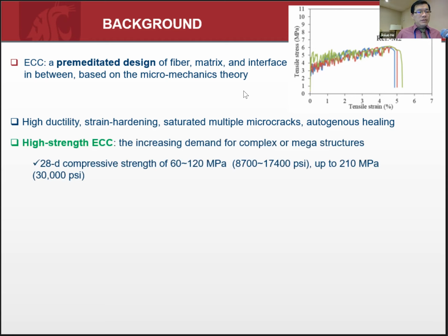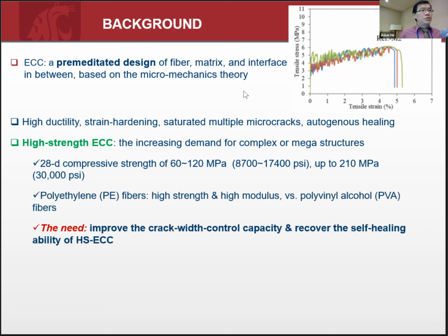Now, in recent years, there's a desire to go for higher strength ECC because traditional ECC is not that high strength. So we're converging with UHPC, even though not reaching the level of UHPC, depending on how you do it. There's some research trying to combine the benefits of UHPC and ECC, but that's not the emphasis here. Here, we're trying to get to better or higher strength ECC. In very recent years, there are a few studies where you can get up to 210 megapascal. How they do it: traditional ECC usually uses PVA fiber, also known as polyvinyl alcohol fiber.